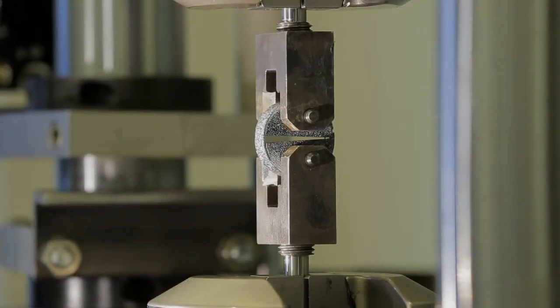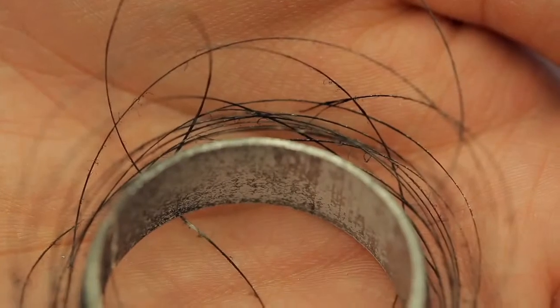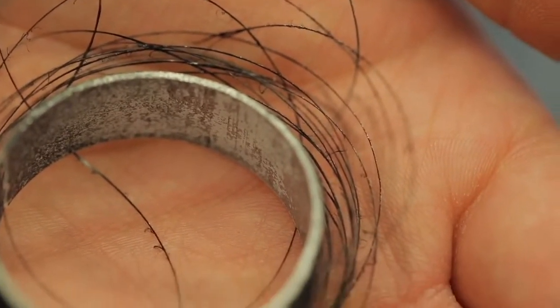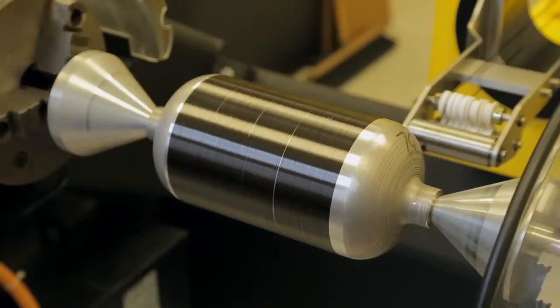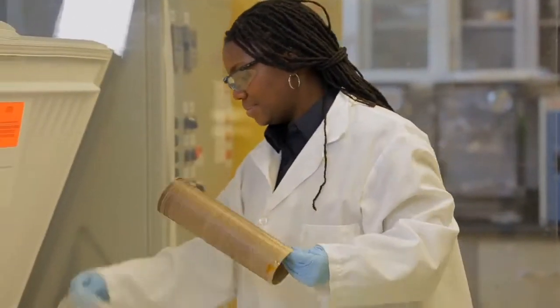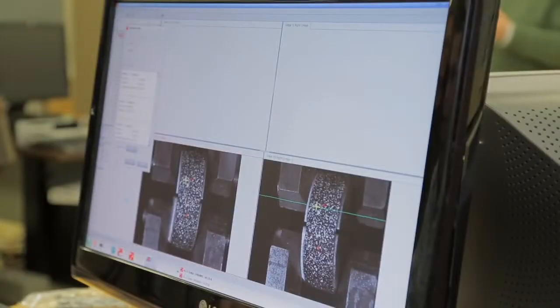Yes, we test the bare aluminum rings first, so we can get a baseline value of the load where the aluminum ring is failing. And then from there, we can subtract the failure from the composite overwrapped material from the baseline so that we can know the tensile strength of the overwrapped material itself. Have you done actually any tests? Do you know how successful or how strong this overwrap is going to be? Yes. Right now, the first layer of material that we're putting onto the rings fell at about close to 600 pounds of force from that small overwrapped material. The overwrapped material that we're testing is only about 0.36 inches wide. Nice. So, you do tests on rings as well as full tanks. Is that correct? Yes. The tanks are the end goal, but for everything that we're doing right now is for the ring test to prepare for the ultimate burst test.